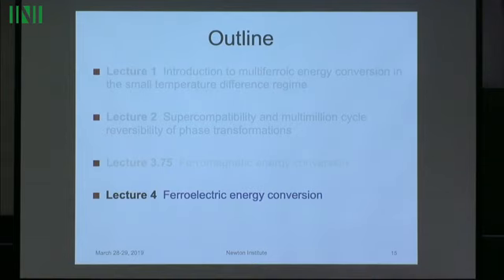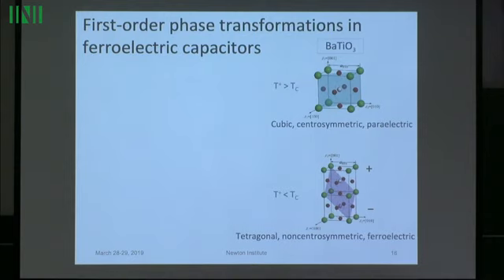The material we chose is a very readily available material, barium titanate. It undergoes three phase transformations, actually. The highest temperature one is this one. It's a cubic to tetragonal phase transformation, and it develops a polarization which is parallel to this elongated axis. So the models for these are okay. I presented in quite some detail the models of phase transformation with ferromagnetism. The models of phase transformation with ferroelectricity are very similar.